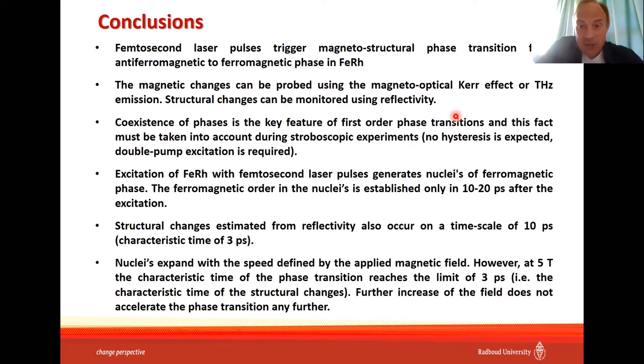Coexistence of phases is a key feature of first-order phase transitions. It's also something that we knew, but what wasn't realized is that it has to be taken into account when you do stroboscopic measurements. You shouldn't expect any hysteresis, and you should do something to guarantee that you probe the very same path. So in our case, it was a double pump experiment. Excitation of iron and rhodium with femtosecond pulses generates nuclei of the ferromagnetic phase. That's known. And what we show is that the nuclei are established only 10-20 picoseconds after the excitation.